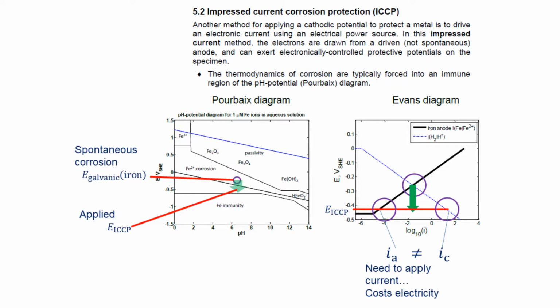So what can we do about that? Well, pretty easily, with an ICCP system, we can apply a new potential to the surface of the metal. So we can apply some E-ICCP by some sort of powered electronic system, and this has the effect in the pH potential diagram of moving our situation close to the border between iron immunity from corrosion and active corrosion.